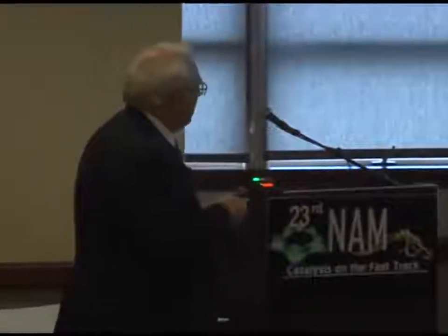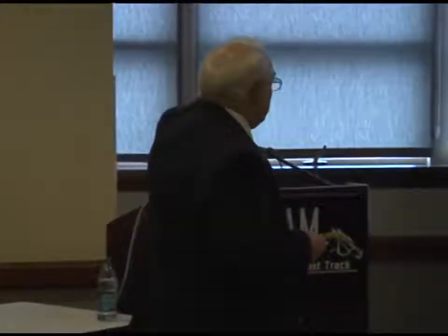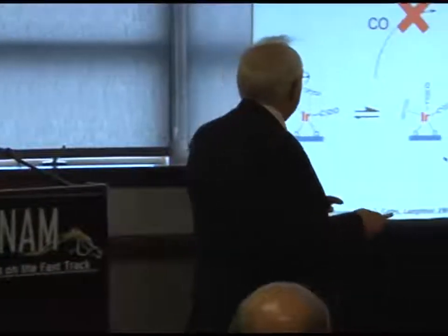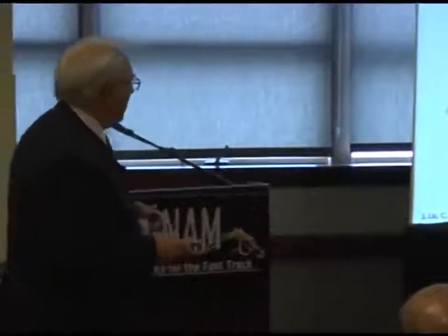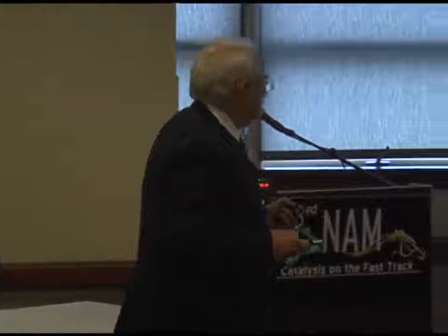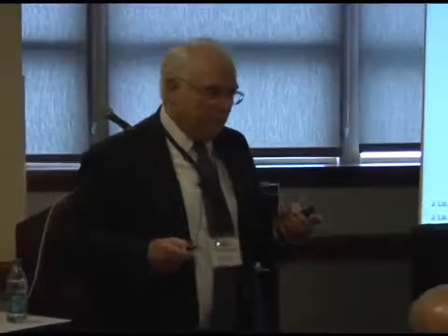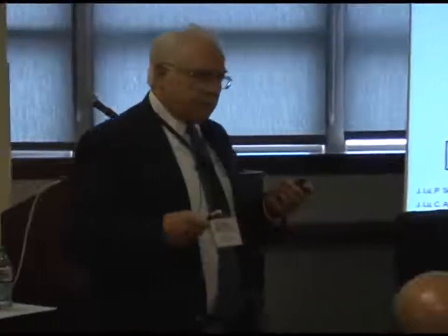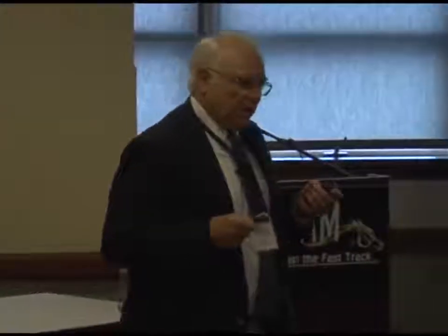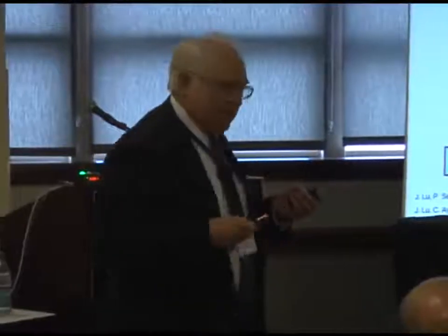If we switch the zeolite from HY to the Chevron zeolite H-SSZ-53, then what we see is similar chemistry to a point, then it's different. So the subtle change in the electron donor character of the ligand going from one zeolite to another has a substantial impact on reactivity. So you expect it's going to affect catalytic activity. Here's some data, ethylene hydrogenation. We use these very simple molecules and test reactions to get the most information from the spectra, because a little ligand like ethylene has a signature that tells us a lot.